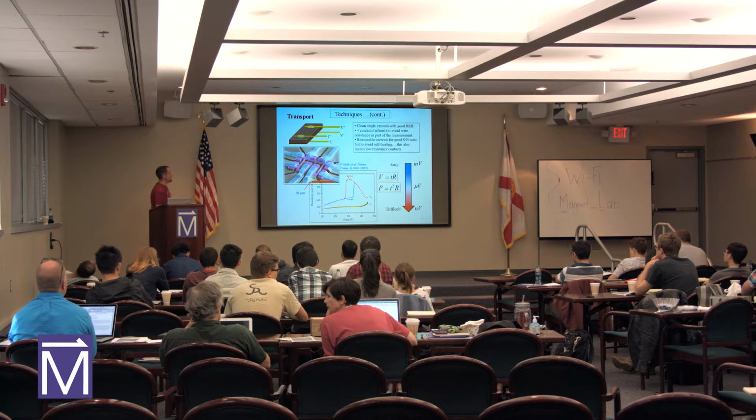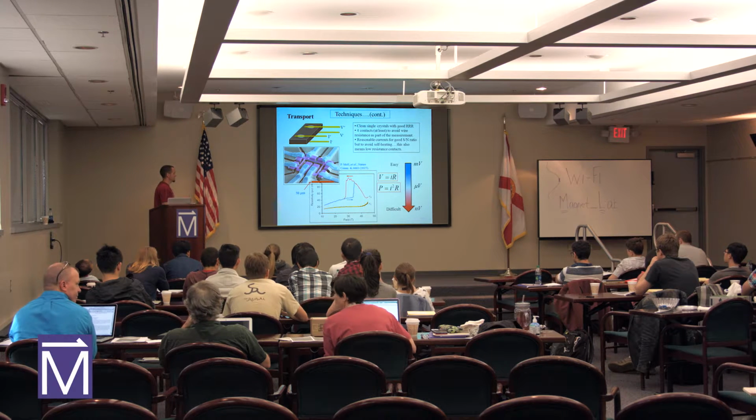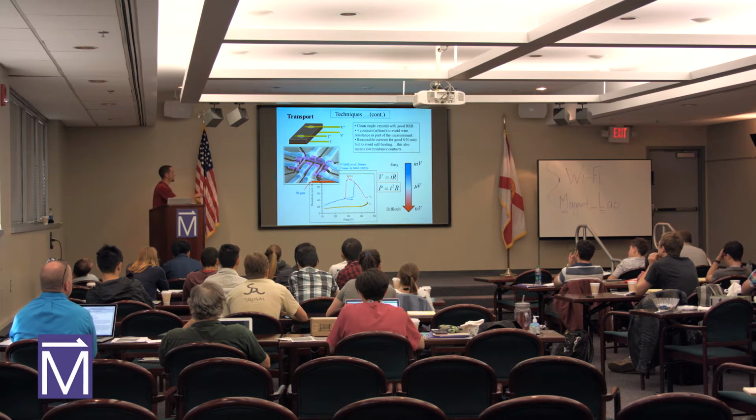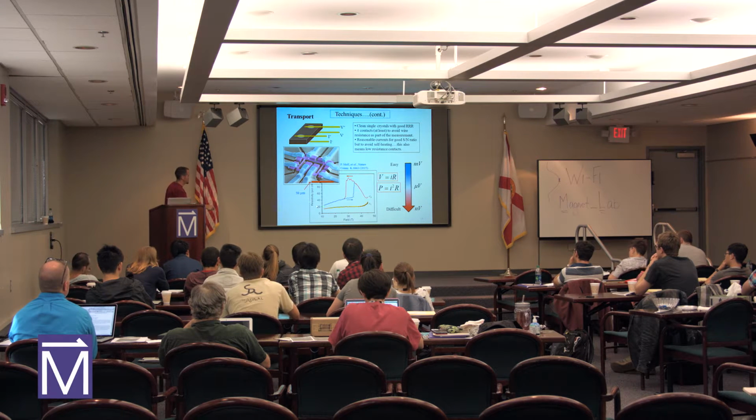This not only has the advantage of being higher resistance, but he can also take a crystal that might be disordered and isolate it down to a clean domain in the crystal, because this whole spacing is less than 100 microns squared. And taking a sample like that, you can get pretty clean results, even in pulsed fields.